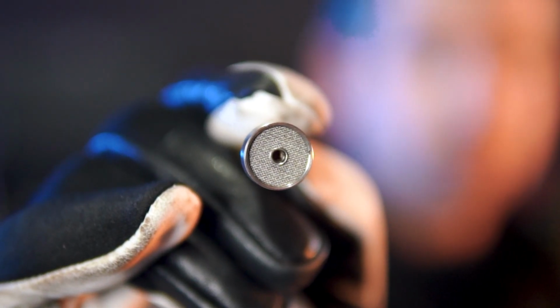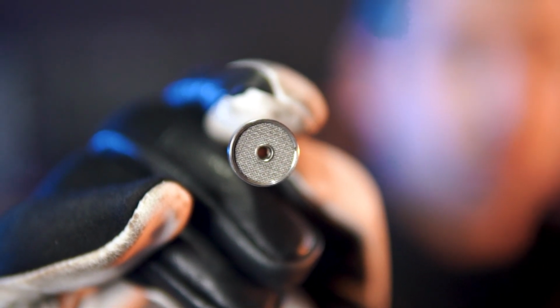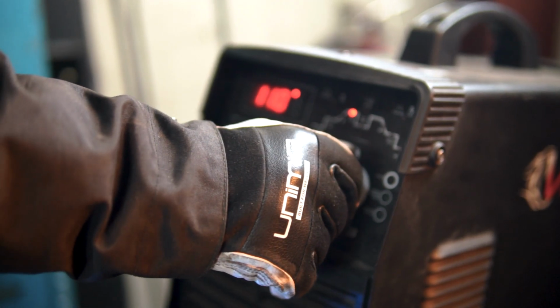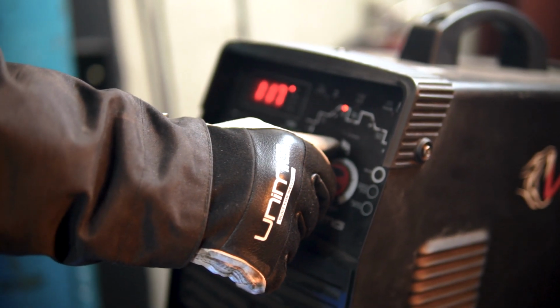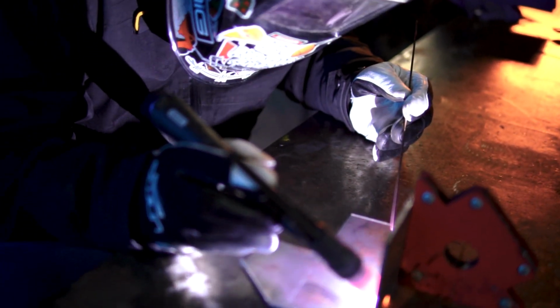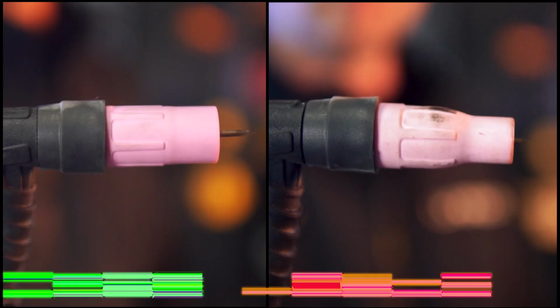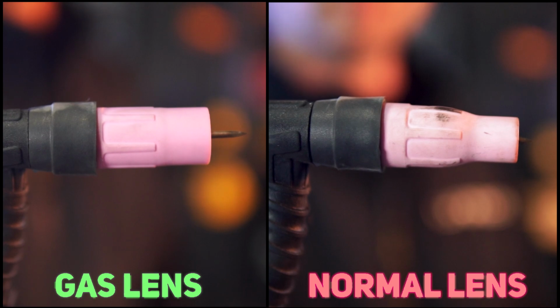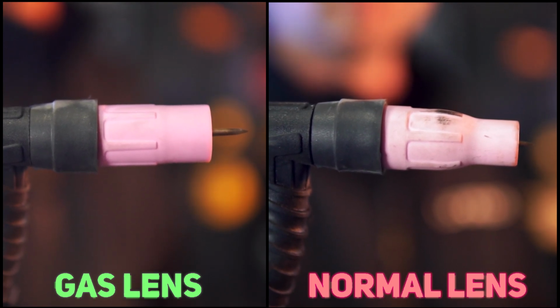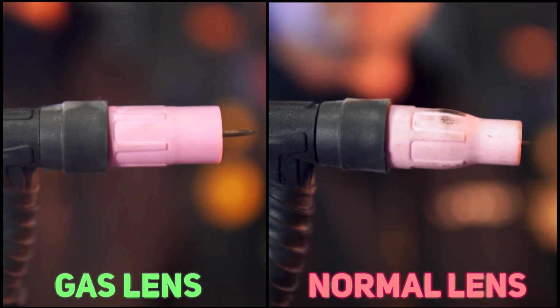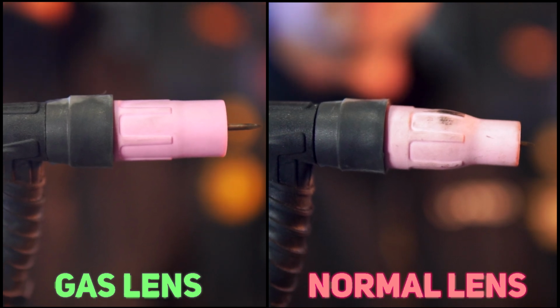The gas lens has a baffle inside that helps distribute the gas evenly, as opposed to a normal setup which can cause turbulence of the gas, leaving the liquefied weld exposed to the atmosphere and prone to weld defects such as porosity. The downfall is that since the shroud is bigger in diameter, it can sometimes be a challenge to get into tight corners. But the good thing is, and I find this to be really handy, that your tungsten can be more exposed beyond the shroud, up to 15mm as opposed to say 3mm on the traditional setup.